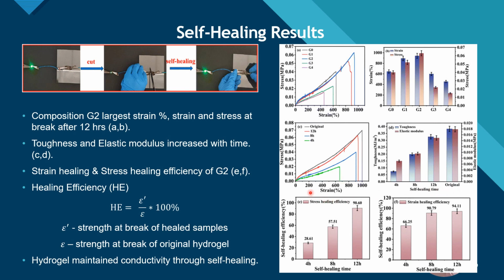We found that the stress and strain at break increased over the 12-hour period from 4 hours to 12 hours. We calculated a stress healing efficiency based off of the ratio of the return stress and strain versus the original stress and strain, and found a healing efficiency of 90% for the stress and 95% for the strain. Lastly, we connected the samples to an LED to make sure that the conductivity had maintained itself through the self-healing. And as you can see illustrated by the illuminated light, it had maintained its conductivity through self-healing.